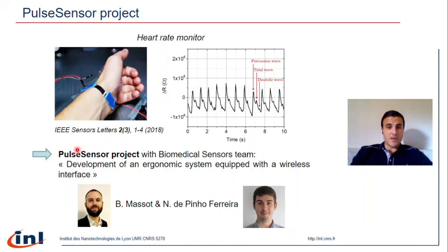From these crack-based transducers, we could also develop a MEMS demonstrator. As you can see on this figure, by simply sticking a flexible sensor on the wrist of a person at rest, we could get some resistance variations that are directly linked to the arterial pulse activity. From this nice signal, we could extract a heart rate in BPM.